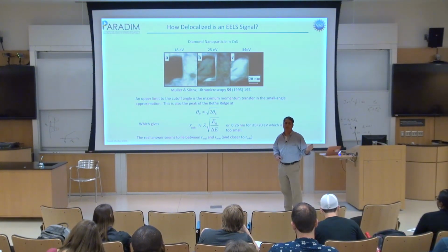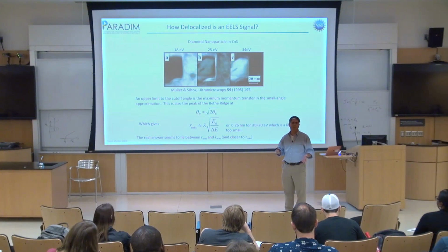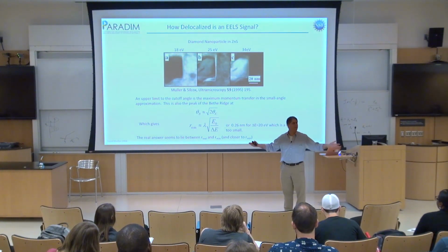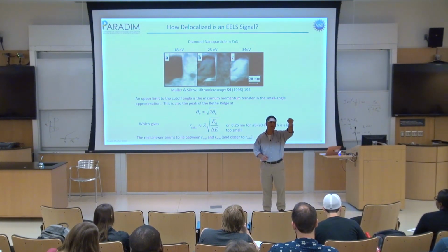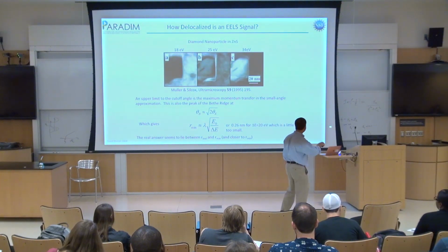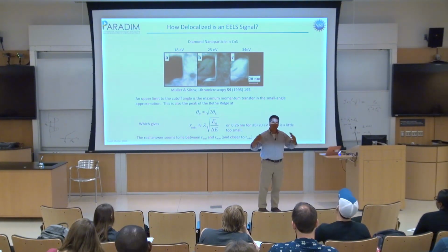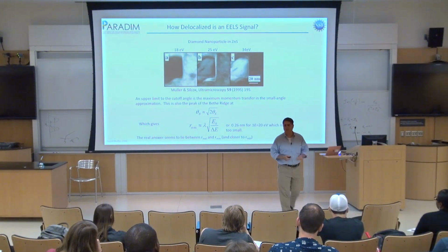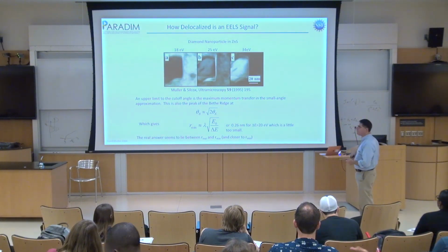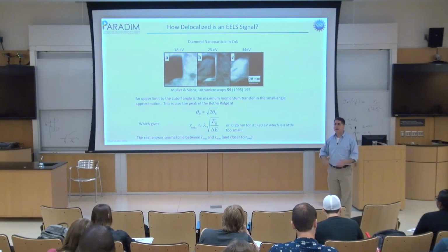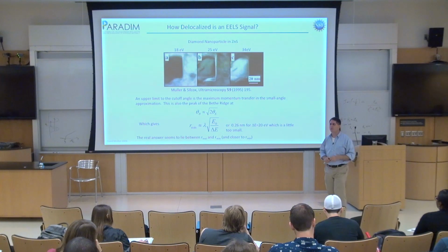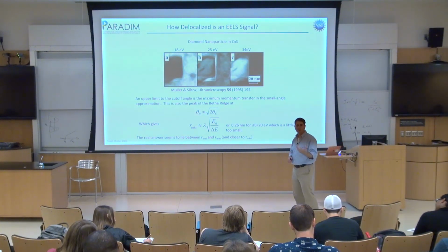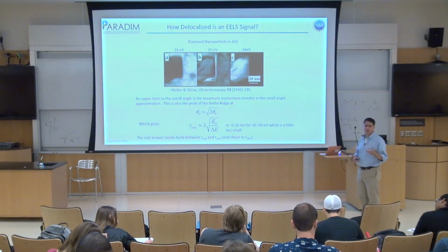And what happens in valence EELS is if I have any electric field in the tails, they're going to couple and they're going to set up very interesting standing waves and boundary conditions. And all sorts of goofy, complicated things are going to happen. In core loss EELS, what's nice is I'm only exciting one atom and I weakly excite the neighboring atoms. But because epsilon 1 is 1 and epsilon 2 is tiny, nothing interesting happens. In valence EELS, these things are very big, and you're going to find out that Maxwell's equations have become important, and I'm setting up standing waves and all sorts of very complicated electrostatic boundary conditions that lead to incredibly complicated spectra that make the interpretation of valence spectra much more difficult than the interpretation of core loss spectra.